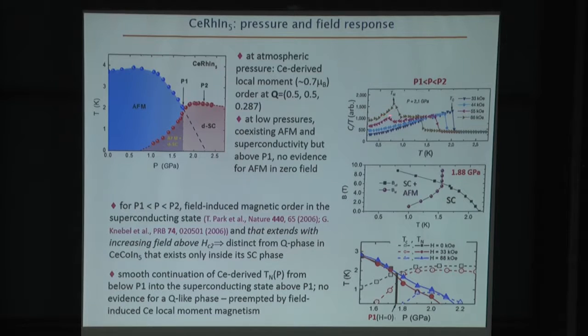Now what's interesting is that this field-induced magnetism that exists in the superconducting state of cerium rhodium indium-5 is qualitatively different from this Q phase in cerium cobalt-5, because we can see here that this field-induced magnetism, while it appears first in the superconducting state, extends into the normal state above the upper critical field boundary. So this field-induced magnetism that appears initially in the superconducting state of cerium rhodium indium-5 under pressure is qualitatively different from the field-induced spin density wave in the Q phase of cerium cobalt-5. And further, as shown by these solid symbols, this field-induced magnetism extends smoothly from below P1 up to pressures close to P2. And we'll come back to this in just a minute.